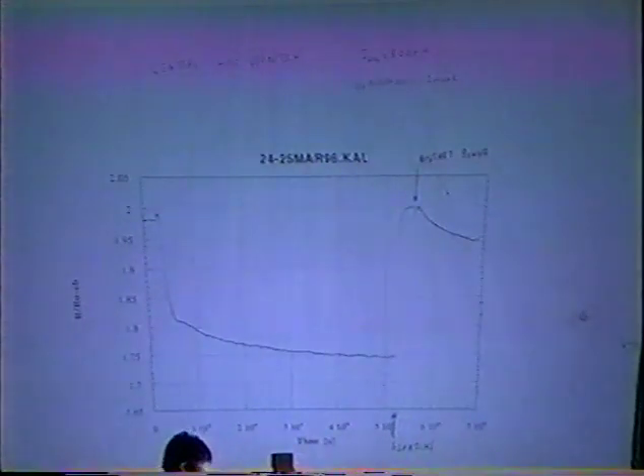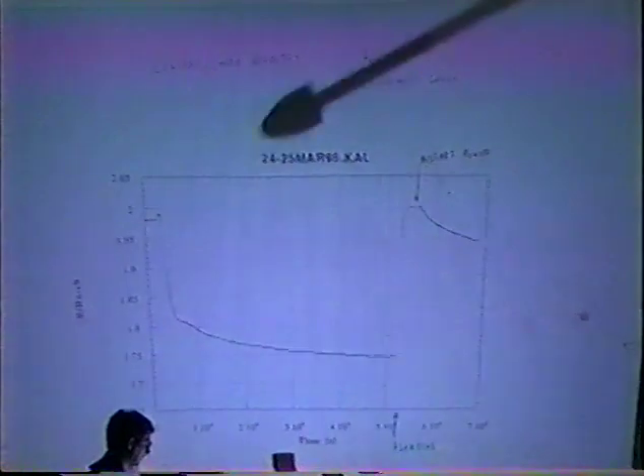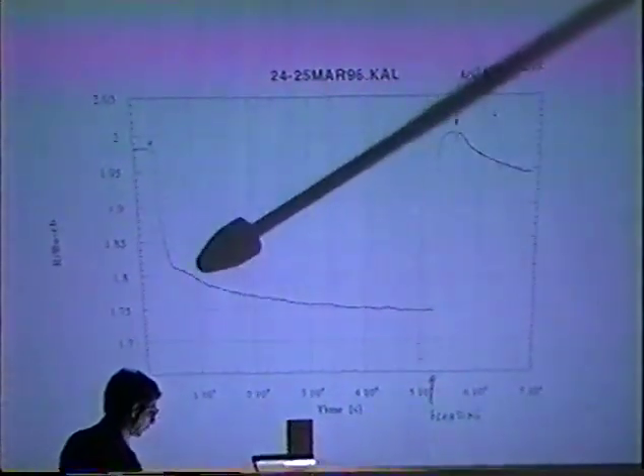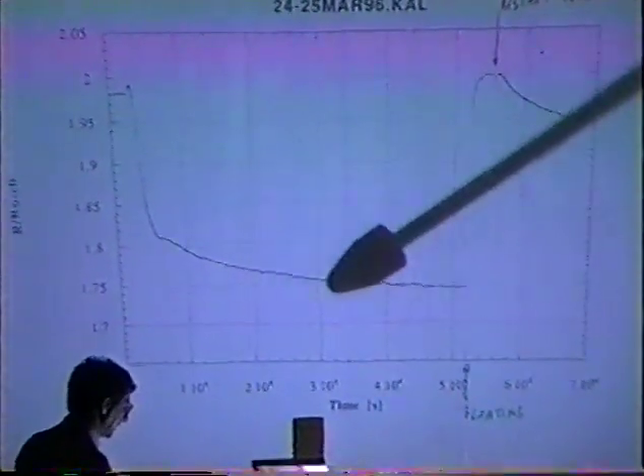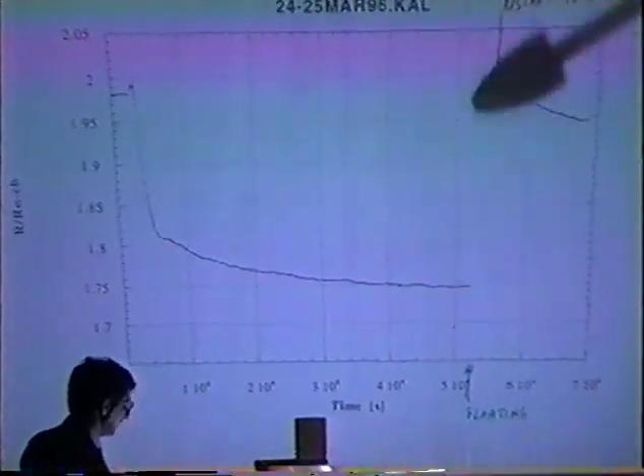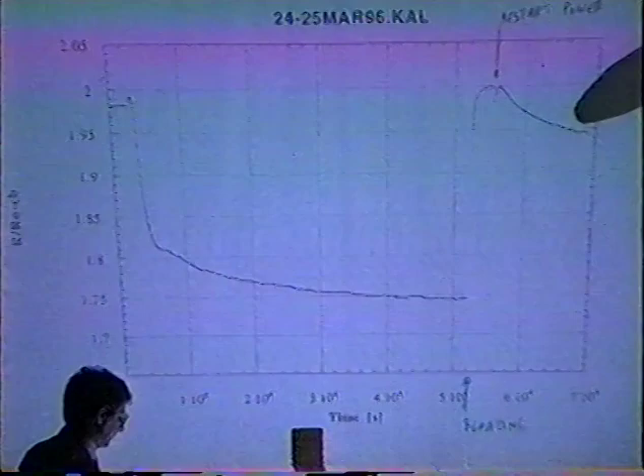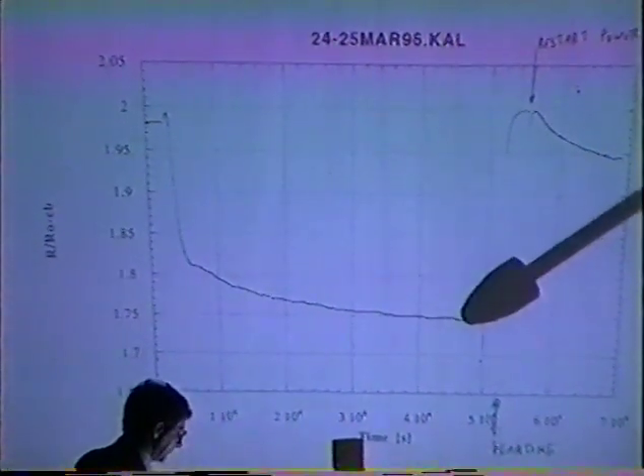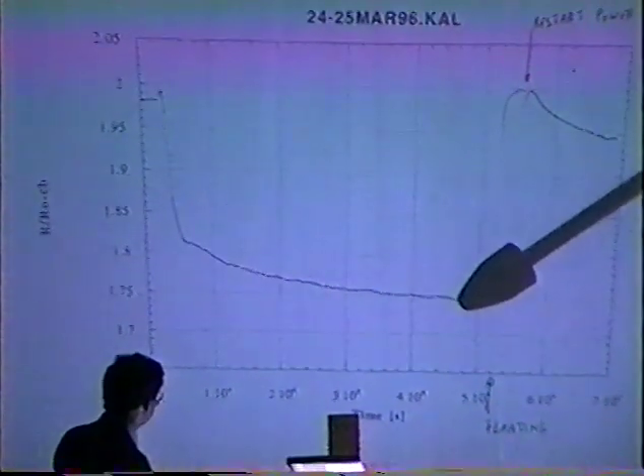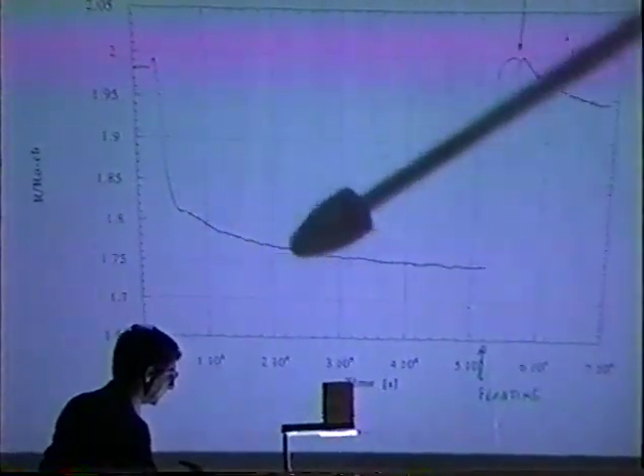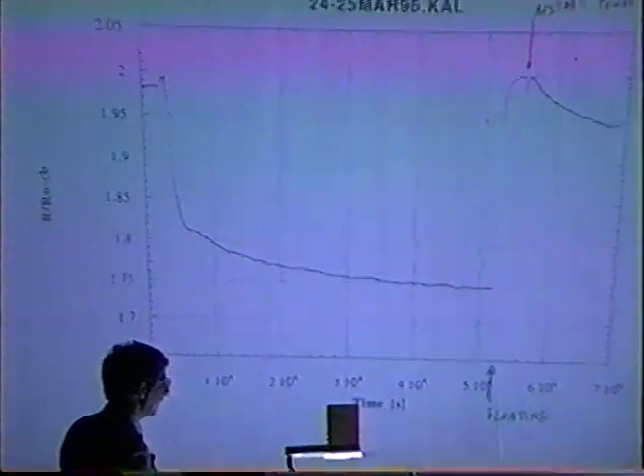And this is the resistance ratio. What happened? We have very large, very fast loading, and the fast loading means a far larger amount of excess heat. Here the loading decreases, the speed decreases, and slowly the excess heat decreases. So we stop again and try to get a good condition. At this point, the excess heat drops almost to 0 in static condition, even though the loading is very large. So just loading means nothing. It's necessary to move the deuterium, to stress this point.